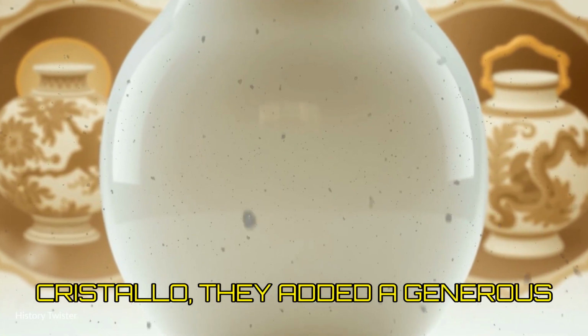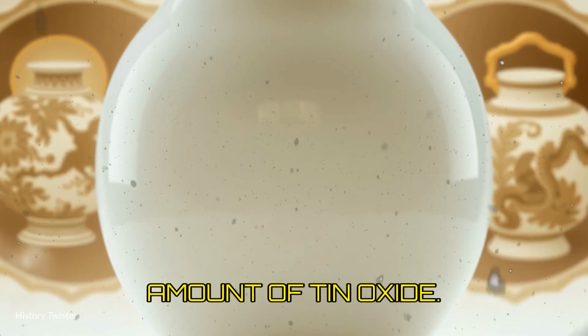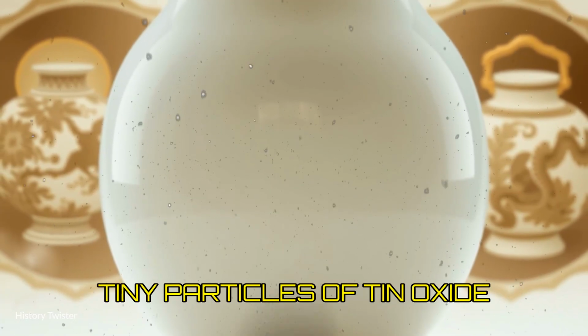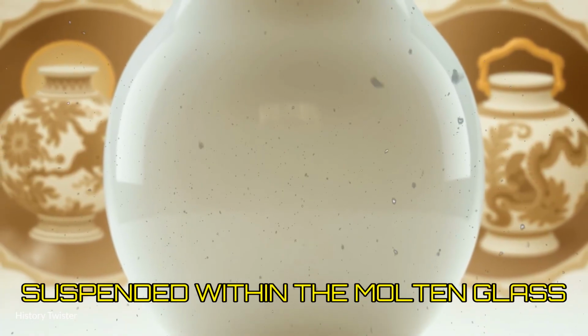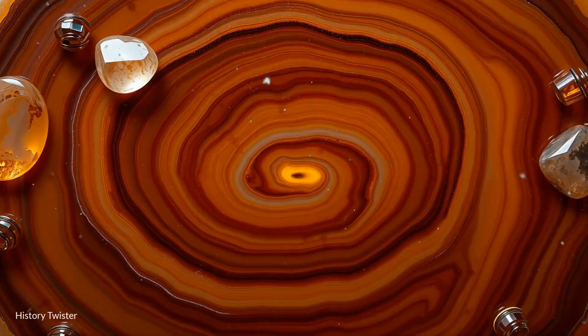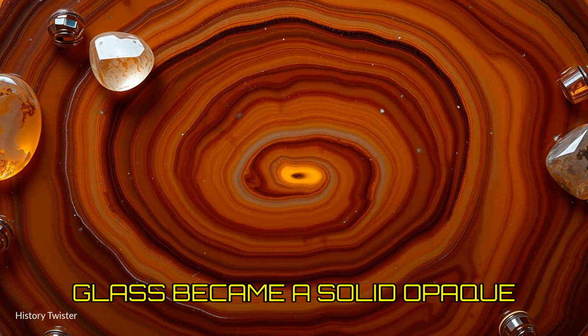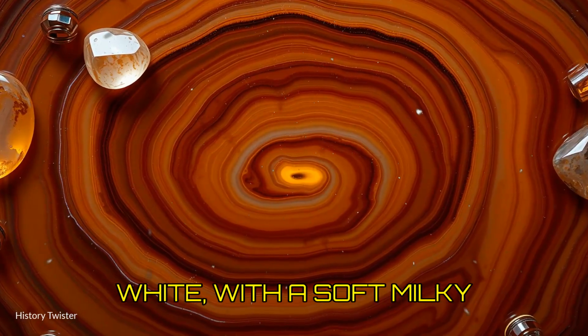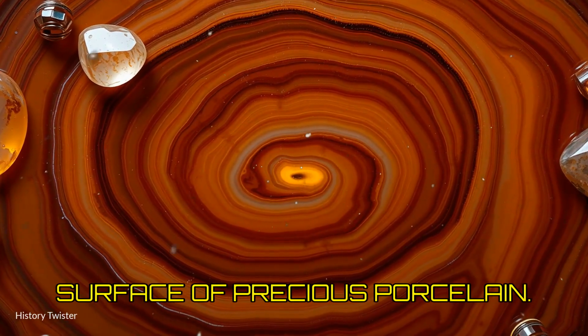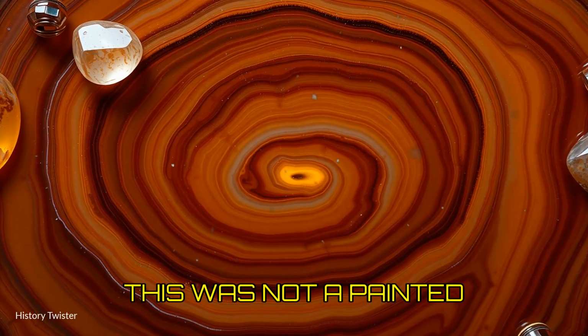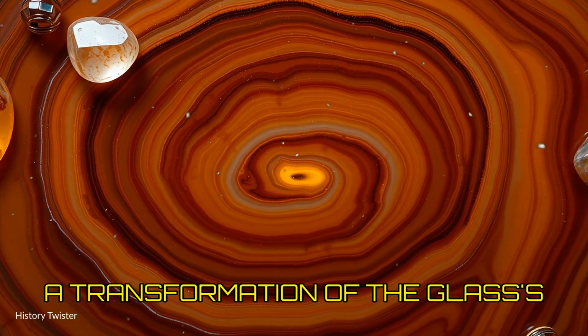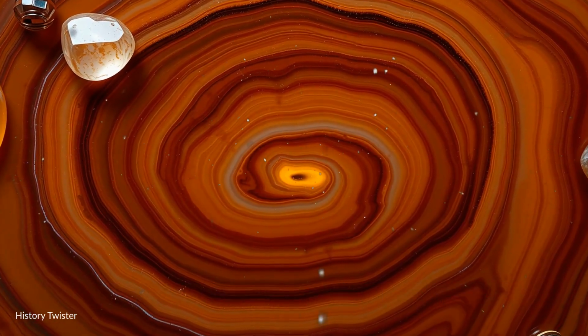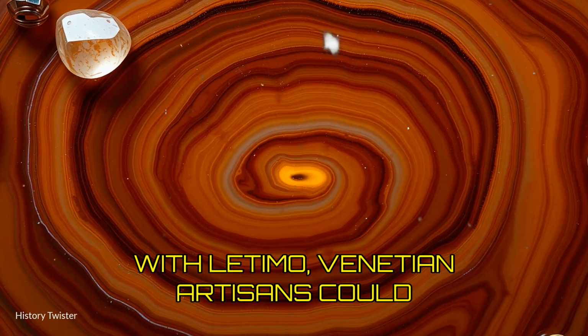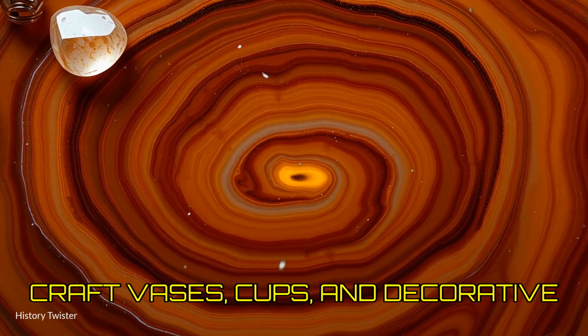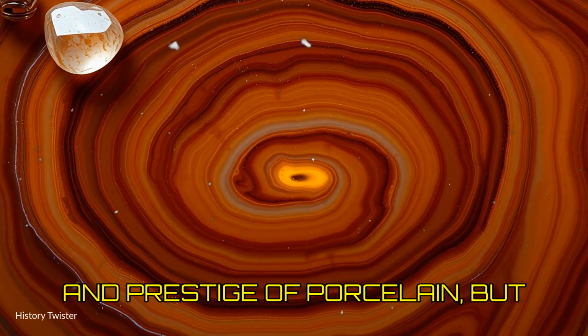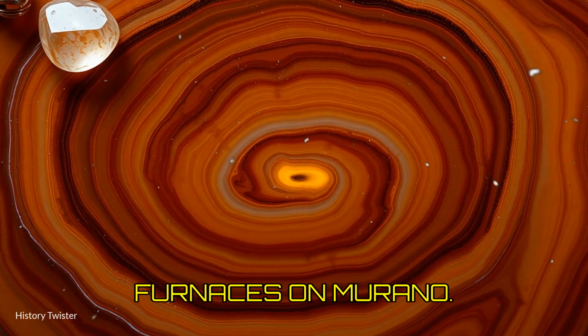To a standard batch of Cristallo, they added a generous amount of tin oxide. When this mixture melted, the tiny particles of tin oxide suspended within the molten glass scattered the light passing through it. Instead of being transparent, the glass became a solid, opaque white, with a soft, milky luster that closely mimicked the surface of precious porcelain. This was not a painted surface or a coating, but a transformation of the glass's very essence from the inside out. With lattimo, Venetian artisans could craft vases, cups, and decorative objects that had the appearance and prestige of porcelain, but were born from their own furnaces on Murano.